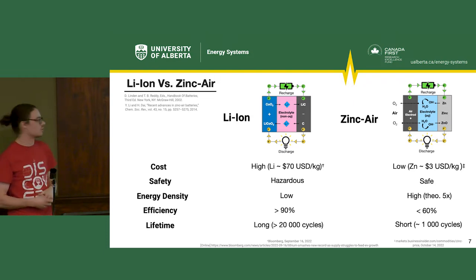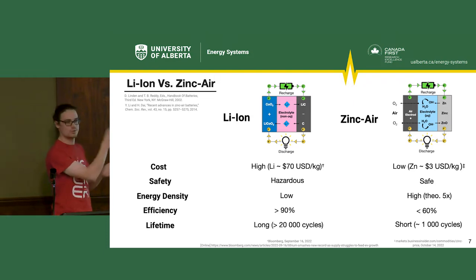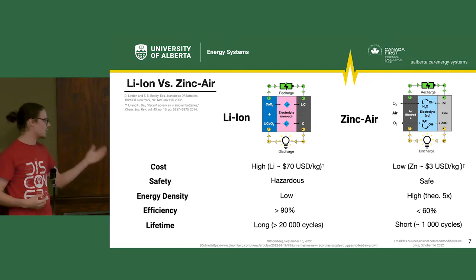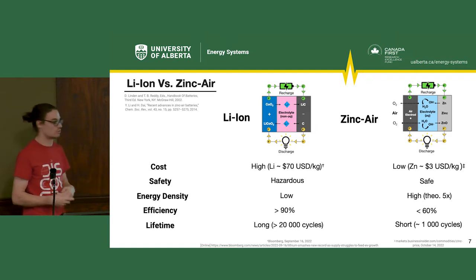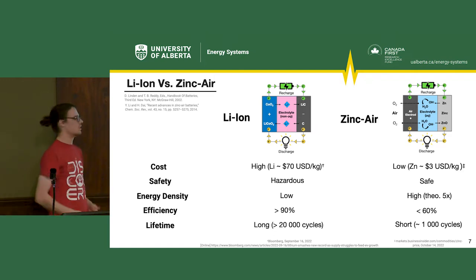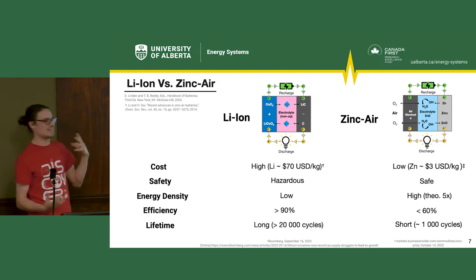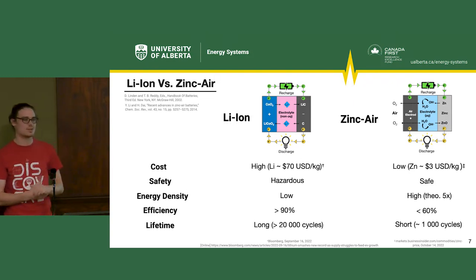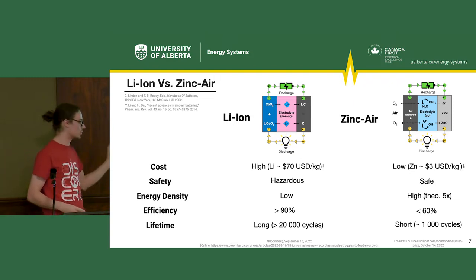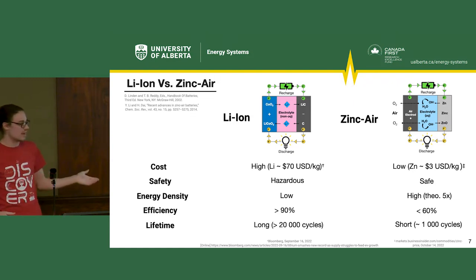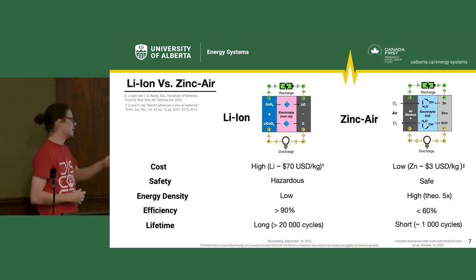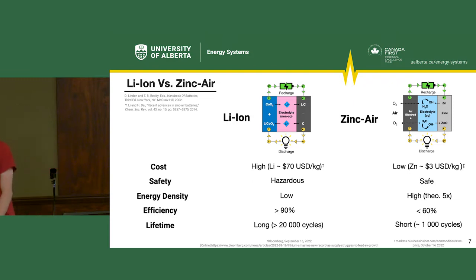Another one is the lifetime. So lithium ion batteries, again, very simple, no issues going back and forth. It can do that almost 20,000 times in a battery. So a lot of charging, discharging. Zinc air batteries, right now, the best ones are around 1,000 cycles. So those are the two main aspects I like to try to improve in my research, is the efficiency values for each charge discharge and the lifetime of the battery.